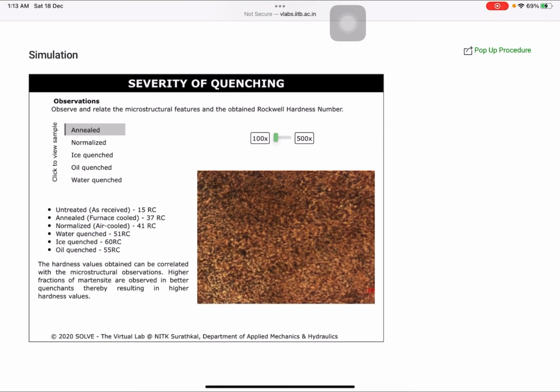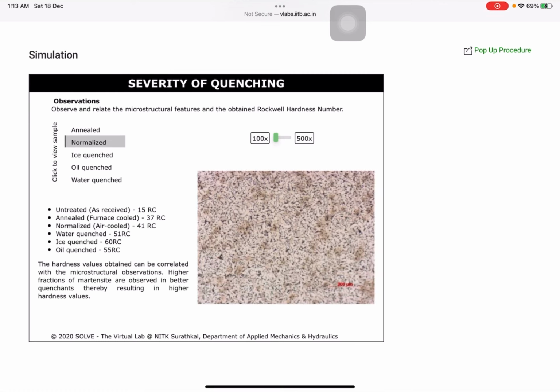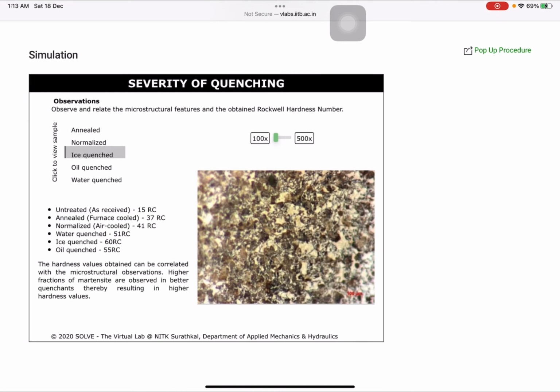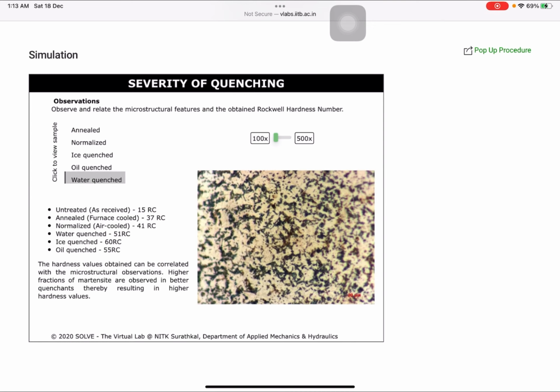So kita boleh tengok satu persatu. Annealed, normalized, ice quench, oil quench and water quench. So berdasarkan observation, kita dapat lihat ice quench mempunyai nilai yang paling tinggi iaitu 60 RC. The hardness values obtained can be correlated with the microstructural observations. Higher fractions of martensite are observed in better quenchings, thereby resulting in higher hardness values.